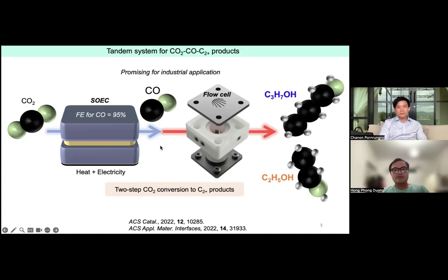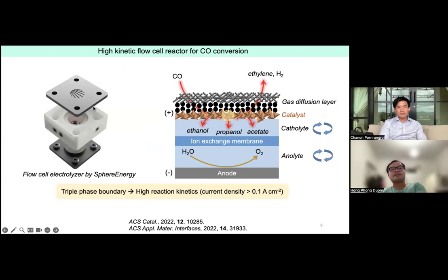Fundamentally, this device is very similar to the H cell or any electrochemical cell. It contains a membrane, electrolyte, electrode, and reference and counter electrodes. But the special point is that this flow cell utilizes a gas diffusion layer coated with the catalyst. This gas diffusion layer contains a porous carbon structure for good conductivity, and on the back side it is also coated with PTFE. The role of the PTFE here is to improve the hydrophobicity of the electrode, which can minimize the rate of the hydrogen evolution reaction, which mainly comes from the electrolyte.